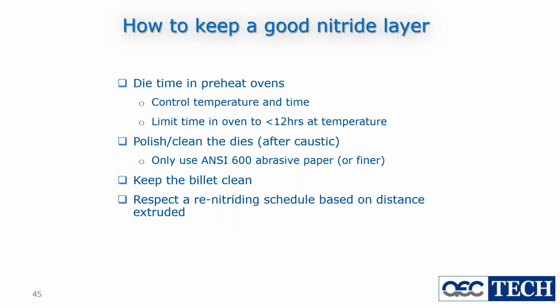And the point being, your nitriding layers build up. What you put in with nitriding number 1 is what's pushed in deeper during nitriding number 2 and pushed in deeper during nitriding number 3. So if we destroy all of the surface nitriding in number 1, the next time we nitride, we go back to number 1 again. We don't build up 1, 2, 3, 4, 5 like I showed you earlier. We just keep doing number 1. And in doing so, we have a sub-optimized nitriding procedure, and our dies will suffer.